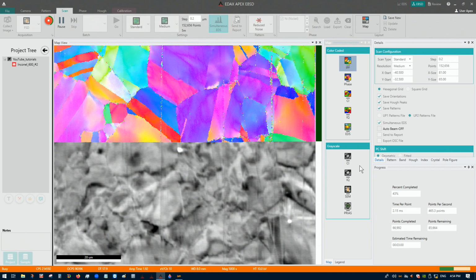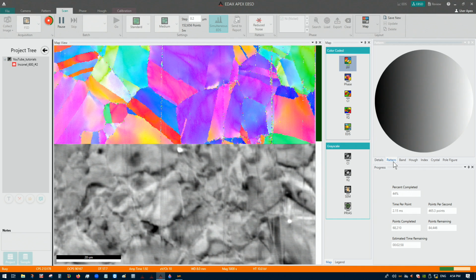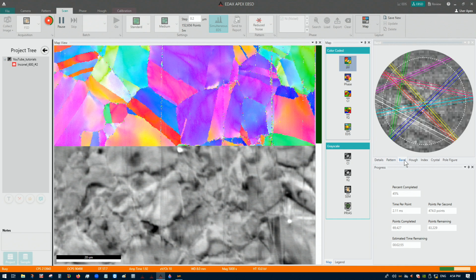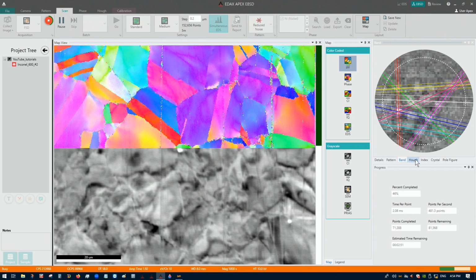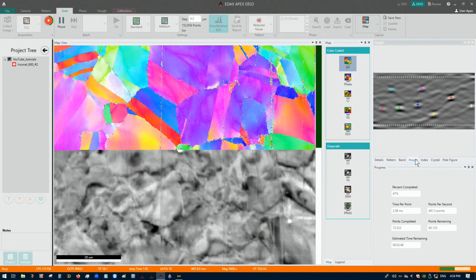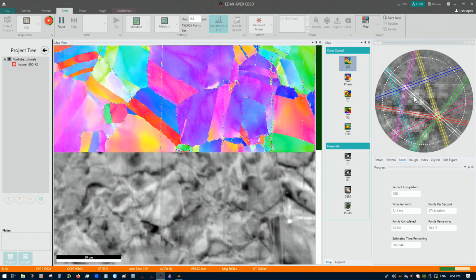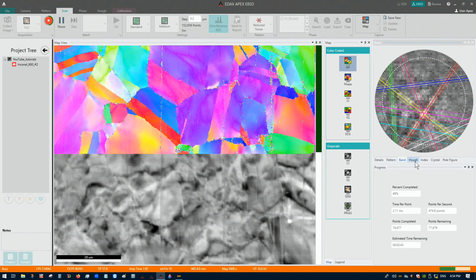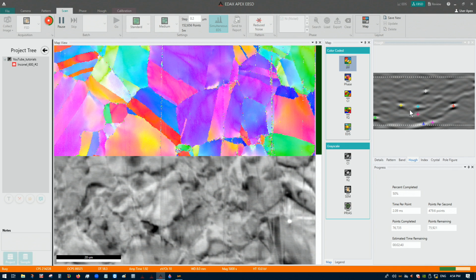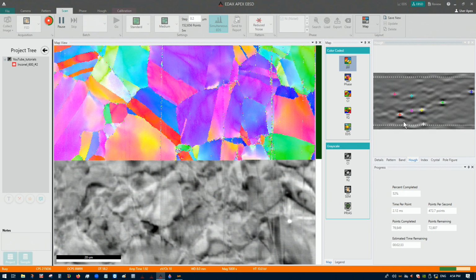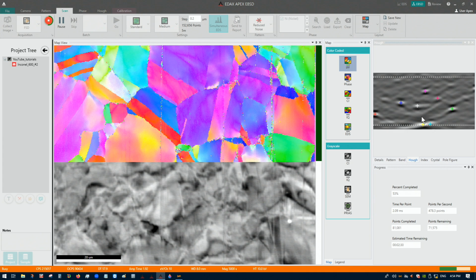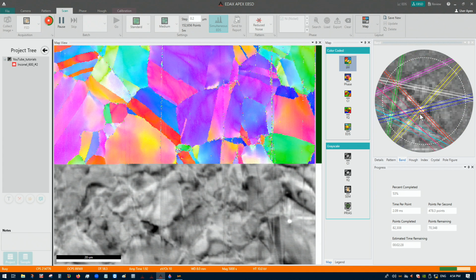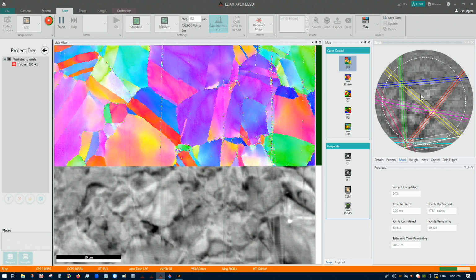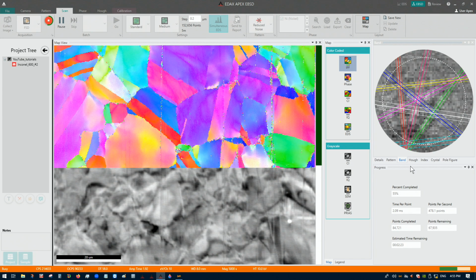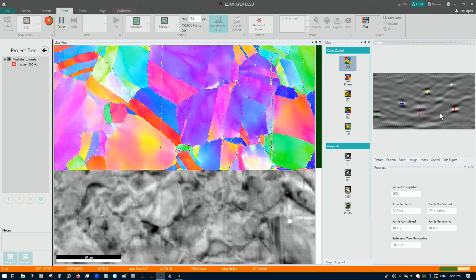Now down here, we can actually look at the live pattern as it's scanning. This is the solution for the Kikuchi bands. This is the Hough transform. So basically the Hough transform is a transform applied to the Kikuchi pattern here, and it's a way of actually figuring out what bands are present. So in the Hough transform here, you see there are these different pluses that are at different maxima in the Hough transform. So if we look at, say, the red plus, that corresponds to the red, well, maybe let's use yellow because there are two kind of close red colors. So the yellow band corresponds to the yellow plus here in the Hough transform.